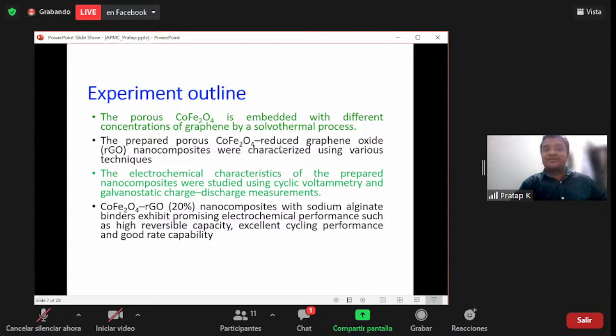The prepared cobalt ferrite materials were characterized using various techniques like XRD, SEM, FTIR, Raman, TG-DTA and so on, to check whether they have formed correctly or not. So it is for structural confirmation. And once we have confirmed the structure, the electrochemical characteristics were studied using cyclic voltammetry and galvanostatic discharge. Among all these composites, 20% RGO plus cobalt ferrite showed very good electrochemical performance, very good reversible capability and excellent cycling performance. So this is the one we are talking about.